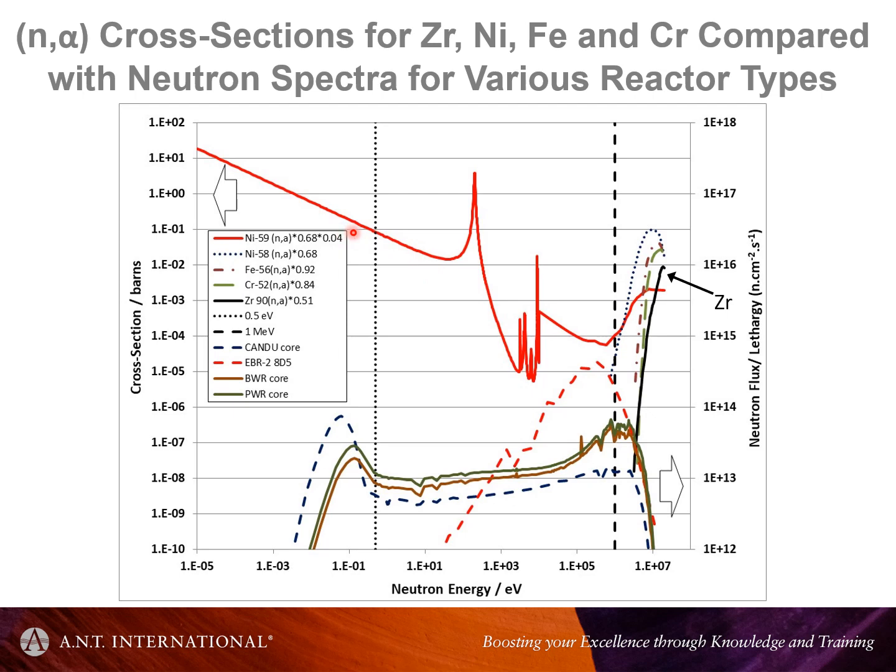So I guess on the plus side, it takes quite a few years to reach the maximum amount of nickel-59 from burn-in and burn-out. But in a fast reactor, that only takes 5 years, and you produce your maximum amount of nickel-59. About 4% of the nickel-58, which is the most common isotope, is converted to nickel-59.